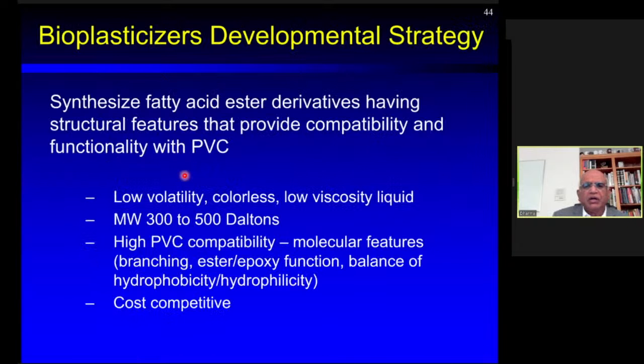based on the literature, we came up with a hypothesis. If we want to synthesize a successful bioplasticizer, the bioplasticizer should be a fatty acid ester derivative having these molecular features that are given here. They should be low volatile, colorless, low viscosity liquids, having a molecular weight of 300 to 500 Daltons. And they should have good PVC compatibility, having the molecular features of branching, ester, epoxy function, balance of hydrophobicity and hydrophilicity, and of course, above all, they have to be cost competitive. We synthesized over 200 compounds, and we were successful with one series of compounds.